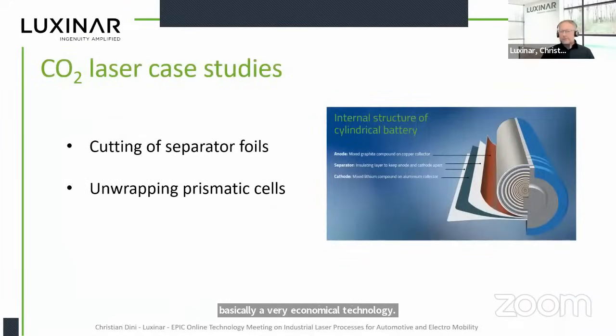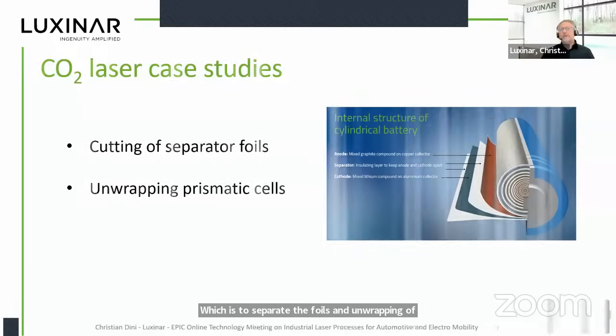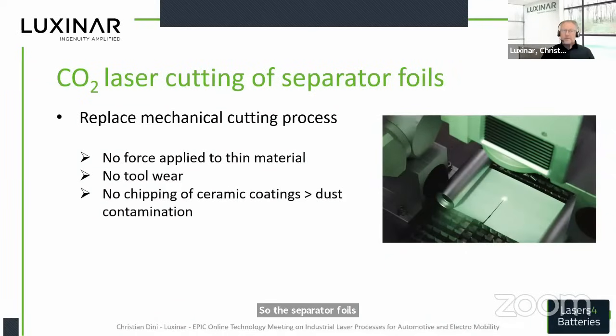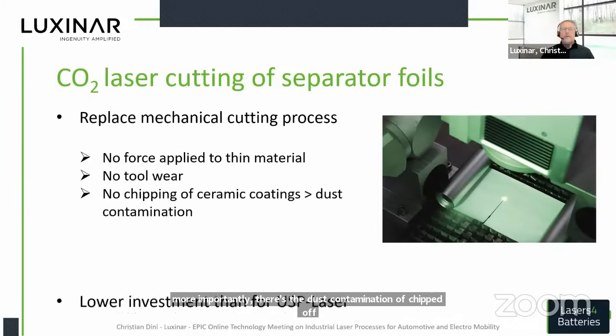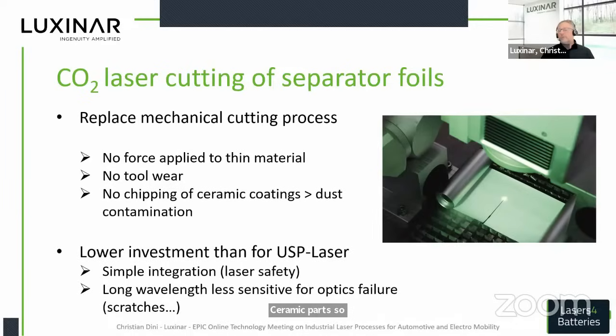Now jumping directly into the two examples, not limited to the two, but the two I chose for today, which is the separator foils and unwrapping of batteries of prismatic cells. So the separator foils, most of the time today, they are still mechanically cut, but with the introduction of ceramic coated separator foils, there's a major issue with that because first, ceramic introduces a new level of wear to the knives, but there's also, and more importantly, there's the dust contamination of chipped off ceramic parts. So if you move to laser, then you have a non-contact, no wear process here.